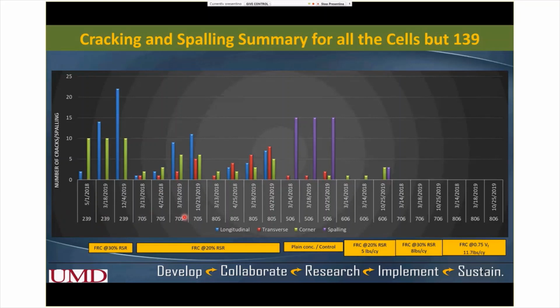Now the comparison between 705 and 805 shows that 705, which had wider slabs, had more longitudinal cracks, and 805, which had narrower slabs, had more transverse cracks. But cell 705, as I said, had 55%, and cell 805 had 28% slab cracked by October 2019. Now, in the other four cells, like 506 through 806, we only saw a few cracks in cell 506, which didn't have fiber, but we saw a lot of spalling, and we didn't see any increase in them in 2019.